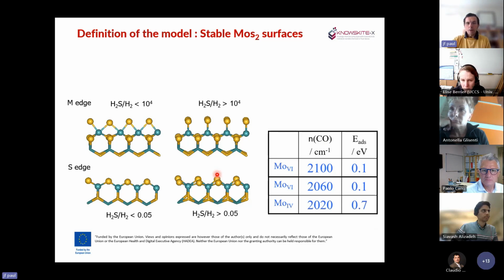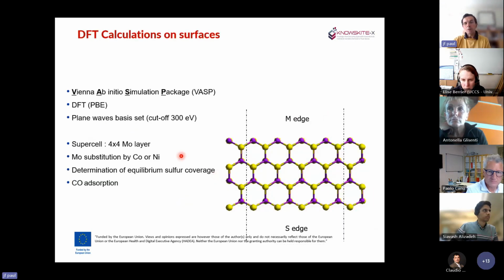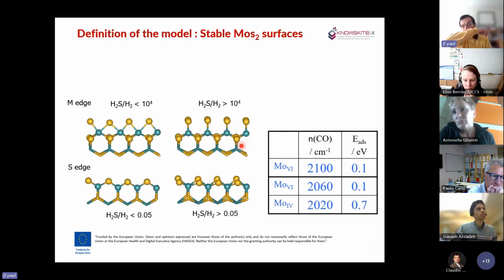If you just perform the adsorption of CO on this type of surface, just on the molybdenum with a very low coordination number, the interaction is very strong, and the frequencies that you can compute are below 1900. So the system is not good at all to describe what is happening. And before computing any properties, you have to be sure that the model that you are using is representative of the system in the experimental condition.